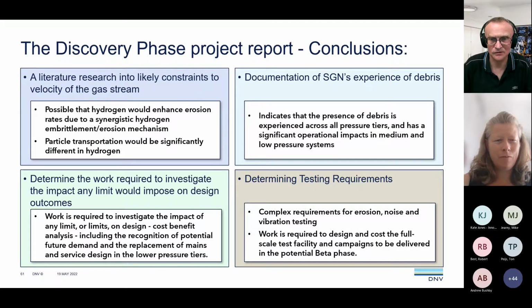And then determining the testing requirements. What we found really is that it's quite complex requirements for the testing for erosion, noise, and vibration. Because we think there's potentially this synergistic erosion mechanism.